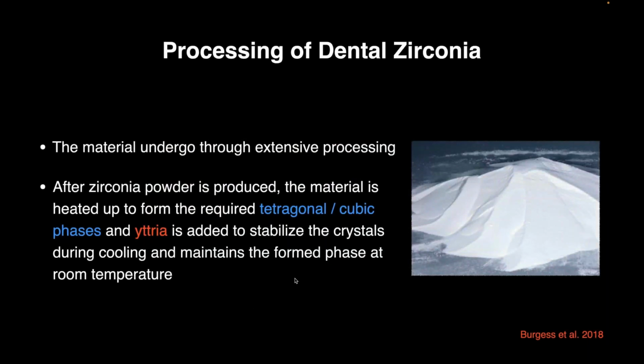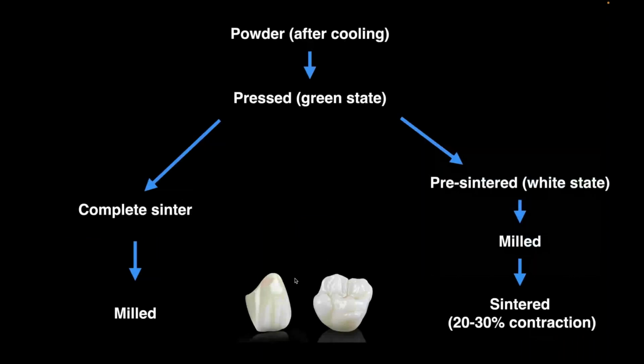On the right picture, you can see the powder, how it's produced, and then it is heated up to form the required tetragonal or the cubic phase, and then yttria could be added to stabilize the crystals during cooling and to maintain it at the formed phase. After that, the zirconia powder after cooling could be pressed, and this is what is known as the green state. That green state is usually milled and then sintered through the sintering machines, or we have the white state material that could be milled and then sintered. And this sintering process will produce 20 to 30% contraction.